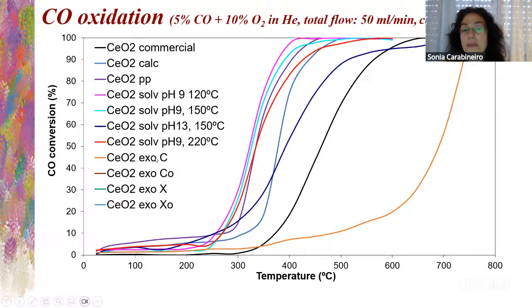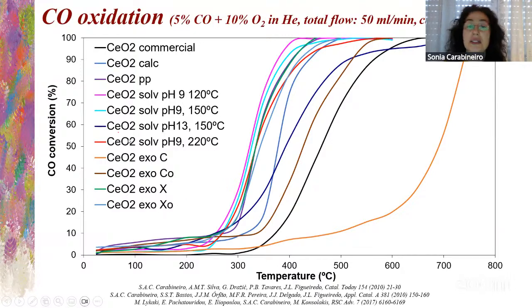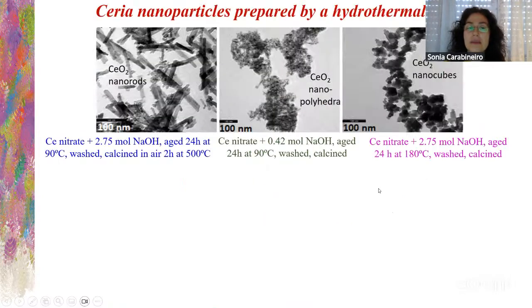Here, it's the exotemplated, but with activated carbon. And what happens is that activated carbon has ashes that decrease the catalytic activity. Because if we use oxidized activated carbon as the template, you see, it's better. However, if we use carbon gel, okay, see, it's there. It's the green one. It's better than the other. And if we use oxidized gel, not much different. So here, the best one was the solvothermal one. This is to compare the different series obtained by this method.